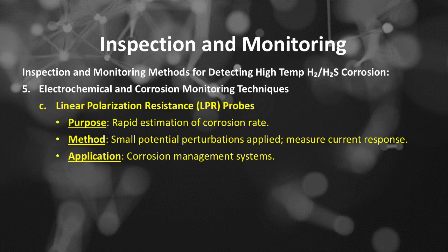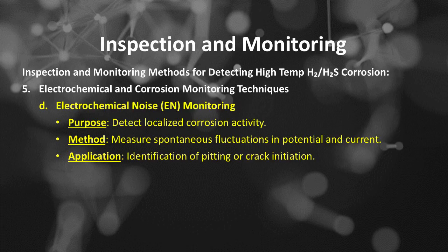Number C is using linear polarization resistance, or LPR, probes. This is purposed for rapid estimation of corrosion rate. The method of using LPR probes is small potential perturbations applied, measuring the current response. The application of using LPR probes is for corrosion management systems. Number D is using electrochemical noise monitoring. This is purposed to detect localized corrosion activity. The method is to measure spontaneous fluctuations in potential and current. The application is for identification of pitting or crack initiation.